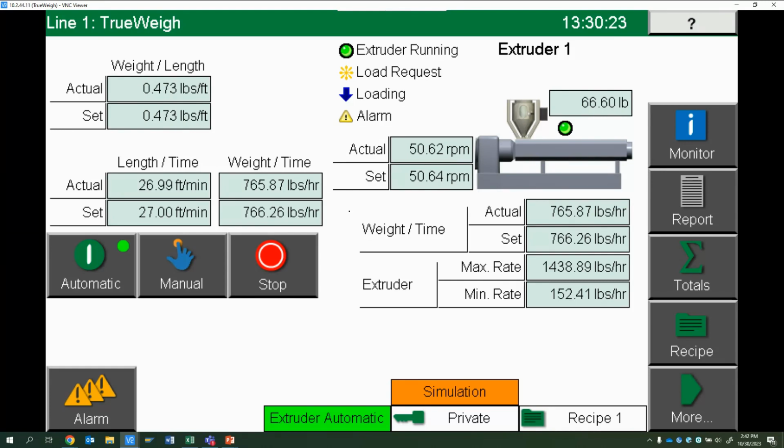If you did not have the gravimetric system to control the pounds per hour going into the extruder, for instance, and if the screen pack began to clog and the pounds per hour started dropping off, then the gauging system being in control of the puller would slow the puller down in order to maintain the product specifications. That's not good because now you're losing time. You're making the right product, but you're making it slower. So having the gravimetric system working in conjunction with the gauging system is yet another way to increase your yields and have very precise control of your product quality.